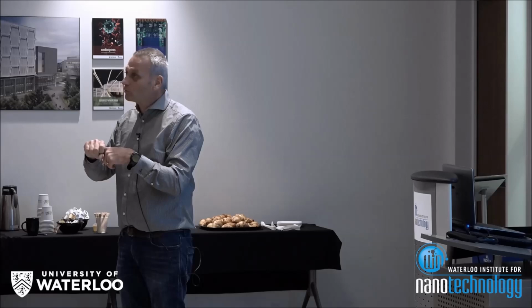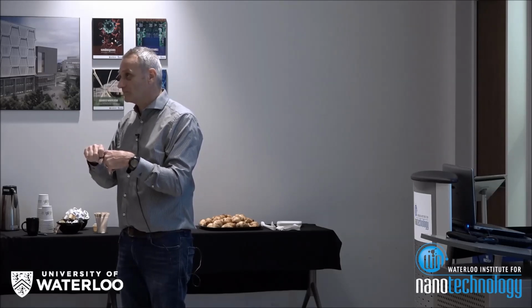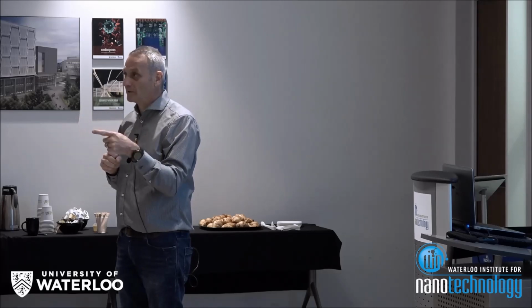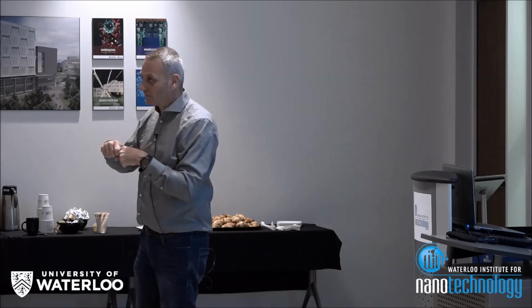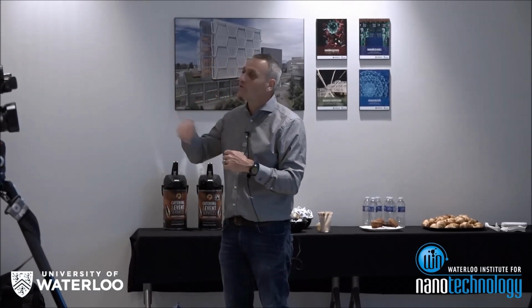Why? Because the PVP around them, even if it's very thin, needs oxygen to start degrading. But we were making experiments under vacuum, so they were very stable. You see why? If you perform thermal annealing in air or in vacuum, that changes things because of the PVP, which can degrade with oxygen, but not in vacuum. So we performed a bit of thermal annealing in vacuum, but we didn't go very far because we should have done a lot of experiments, and the PVP is very tricky.